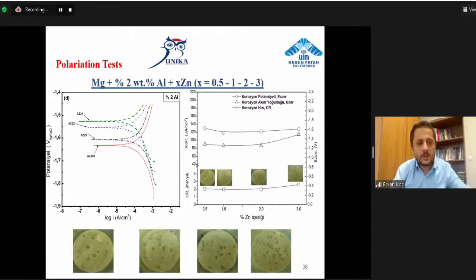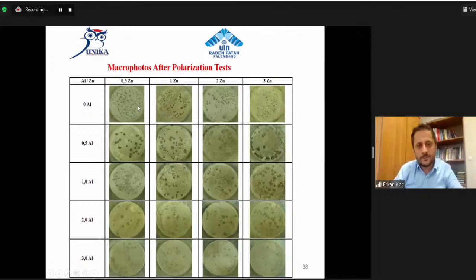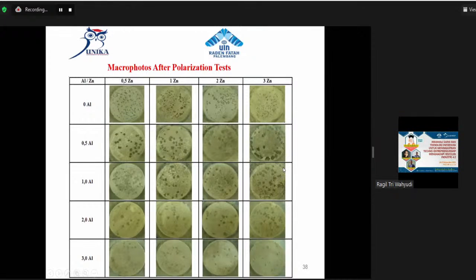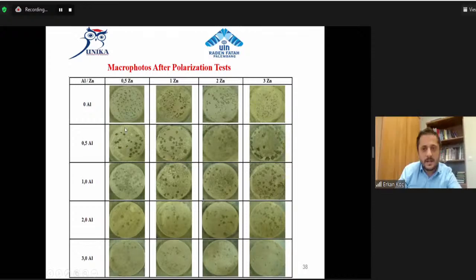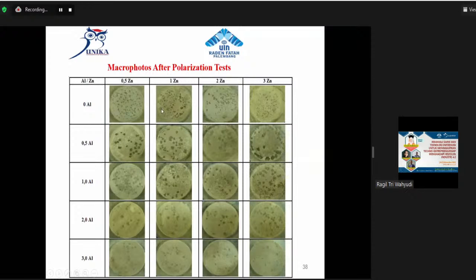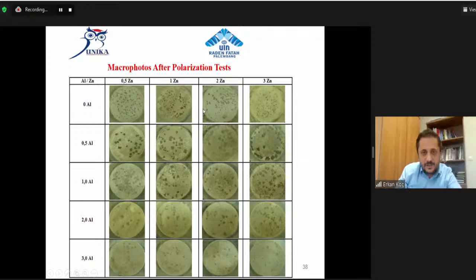When the macro pictures obtained from the polarization curves are examined, here you can see I have 20 kinds of magnesium alloys. It was observed that pits on the surface decreased with the increase of both aluminium and zinc. Here aluminium is increasing; on the horizontal side zinc is increasing.